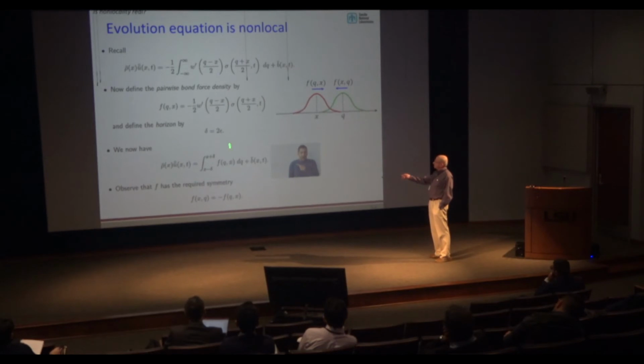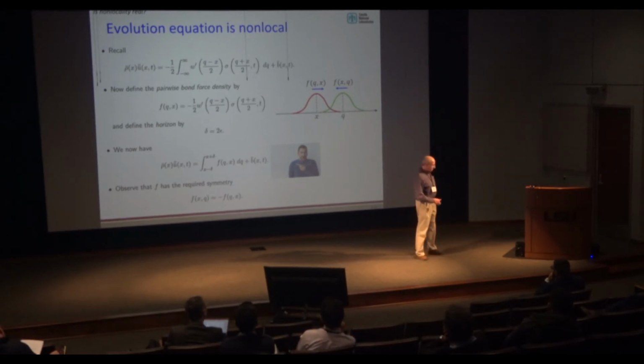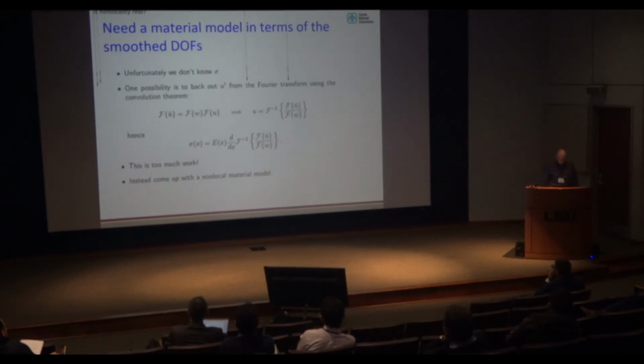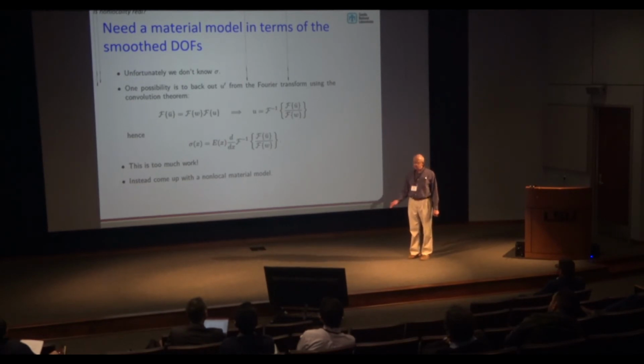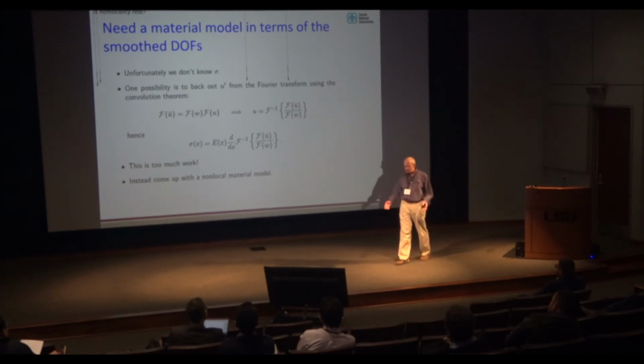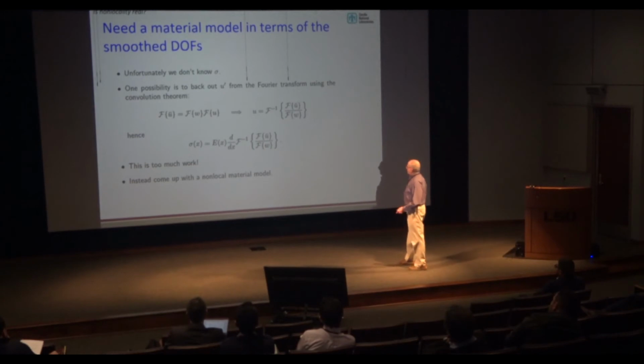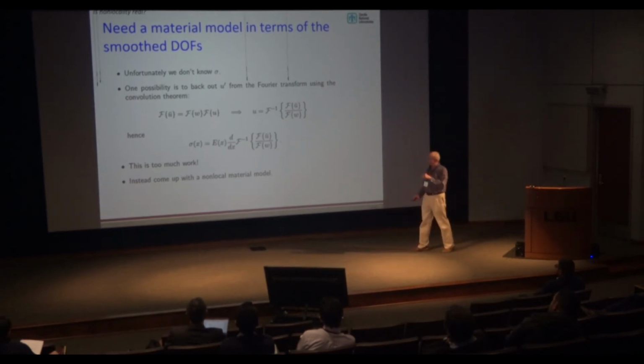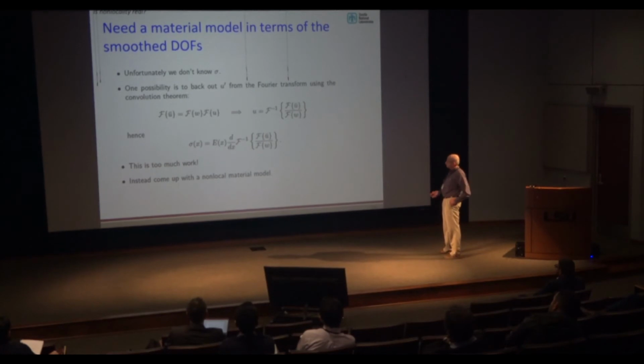And this F defined here is the bond force, and it obeys the required anti-symmetry between switching the values of X and Q. So I claim that this sort of motivates the use of non-local mechanics models, even when the underlying physics is local and there are no obvious long-range forces to deal with. So the expression I came up with for the bond force densities is almost peridynamics, and I say almost because it doesn't really contain a material model that will allow us to evaluate sigma and therefore F at any X and Q.